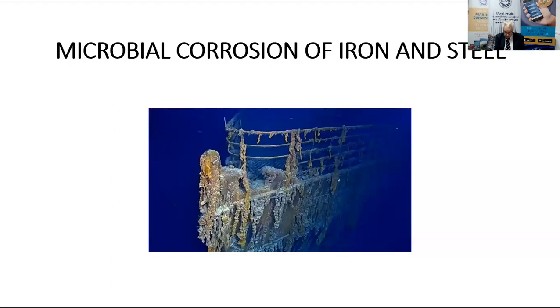Sulfur oxidizing microbes leave the bottom of the pit covered with a bright silvery white coloured, very hard substance. Now, talking about the oxidizing bacteria, these oxidizing bacteria are from the genus Thiobacillus and are usually referred to as SOBs and perform the oxidization of sulfur to sulfuric acid. The acids produced can cause deep pits to appear in the ground metal, though their involvement in the corrosion process is only slight compared to the sulfur reducers.